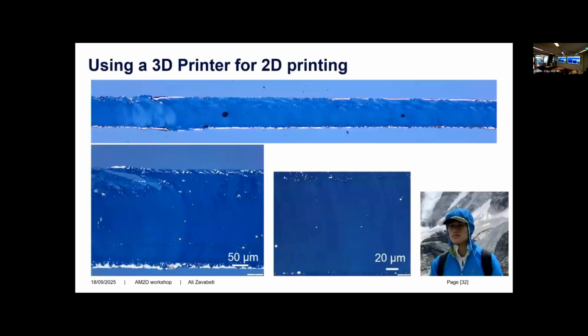Also, at the end of my presentation, I would like to show you what my student is doing at the moment. He's also printing these 2D layers, using a 3D printer to print in 2D. That stretch is basically just a 2D oxide. He just used a small pipette tip with a liquid metal inside. And this is a 3D printer that he just moves, and it leaves a 2D layer behind, which is really great. What happens is he goes forward, and there is a liquid metal residue, because of the high surface tension of liquid metal, it just goes back to join the nozzle.